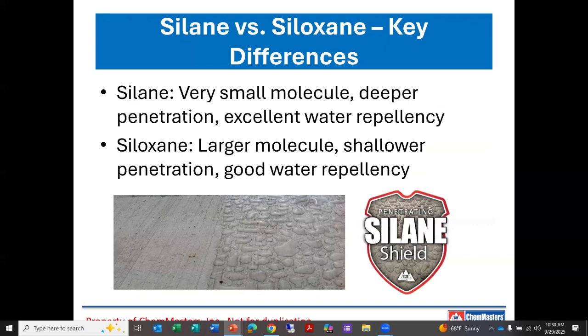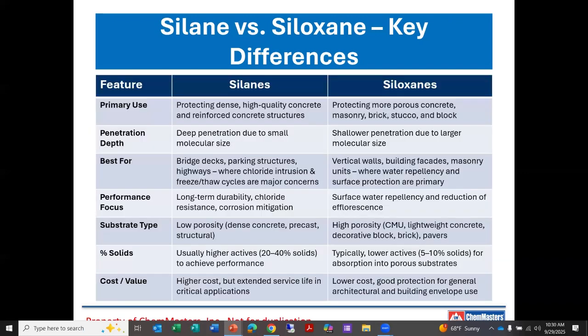So the key takeaways, silane is a very small molecule, deeper penetration, excellent water repellency, preferred for denser surfaces. Siloxane, little larger molecule, little shallower depth of penetration on dense concrete, very good water repellency, maybe preferred on more porous substrates. And again, here are some of the key differences. We've covered several of them previously. Dense substrates for silanes, more porous substrates for siloxanes, a little different depth of penetration, particularly when it comes to dense substrates. The silanes have the smaller molecule, which will penetrate deeper.